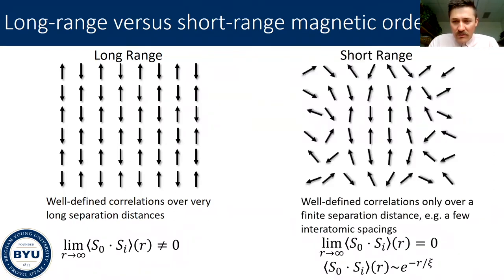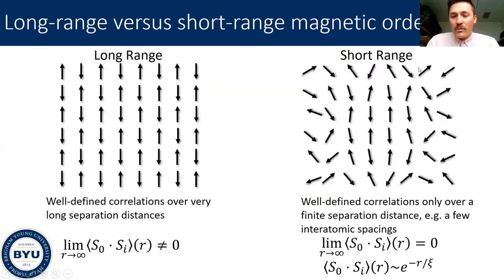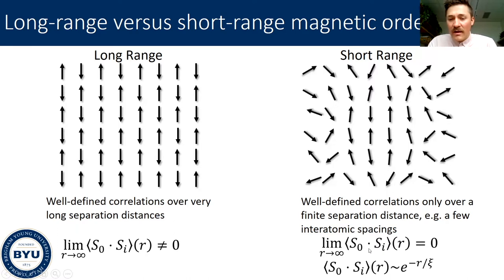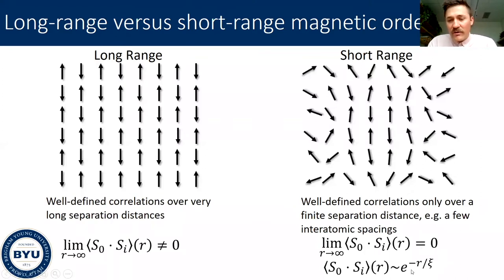But what I'm focusing on here is short-range order. If we take a spin at the center of our picture and look around it, there is certainly a net antiferromagnetic correlation nearby. But as we move further away, the correlation becomes more and more random, less well-defined. So our well-defined short-range correlations only exist over a finite distance, maybe a few interatomic spacings. The limit of this spin correlation function, as the separation distance goes to infinity, will be zero — there will be no long-range order. Nevertheless, we'll have well-defined correlations on short length scales. Typically, the correlation function will die off exponentially, where ξ is our magnetic correlation length.